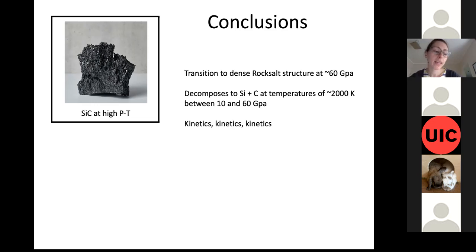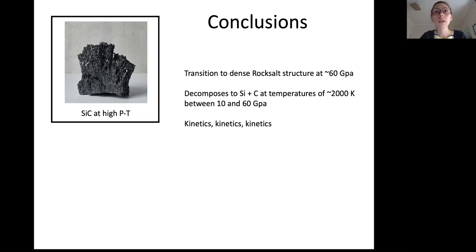Right? And again, what we keep finding is that kinetics is a big part of the silicon carbide system. So in the rock salt transition, there's a large hysteresis that we observe. And again, in the decomposition, we never observe complete decomposition of all of our silicon carbide going to silicon plus carbon. And so this is partly because of the experimental setup. When you're heating diamond cell experiments, you're not going to be leaving it there for hours. It's going to be seconds, maybe minutes if you're kind of risky. And so getting to achieve equilibrium in these systems is something that would be really interesting.